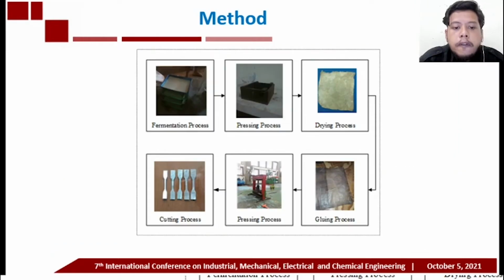The first step is the fermentation process using Acetobacter. The fermentation process takes 7 days until the coconut water becomes solid. In the next process, the solid coconut water is pressed using variation of compressive weight: 50 Newton, 100 Newton, and 150 Newton, to reduce the water content. The solid coconut water is dried for 4 days under the sun.